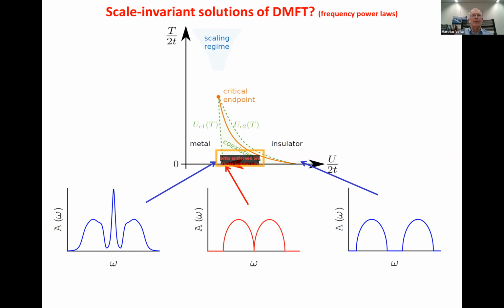This is the point where there's room for a power law in the spectral function at zero frequency, shown here in the middle of this plot. That is the only possibility in DMFT for the single band Hubbard model to produce a frequency power law. So this would occur in the insulator at the point where the Mott gap closes.